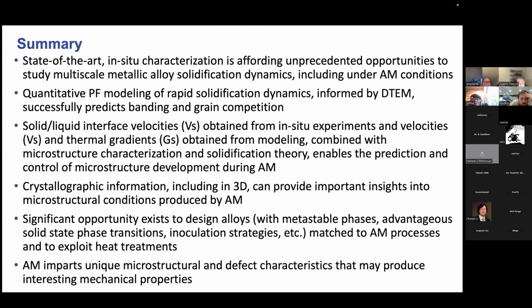So I think with that, in conclusion, state-of-the-art in situ characterization really allows us to understand solidification dynamics, including with additive. We've shown quantitative phase field modeling can predict the banding and grain competition. The G's and V's are really important, and when we combine that with the characterization and the theory, it really allows us to move forward with predicting and controlling the way microstructures develop.